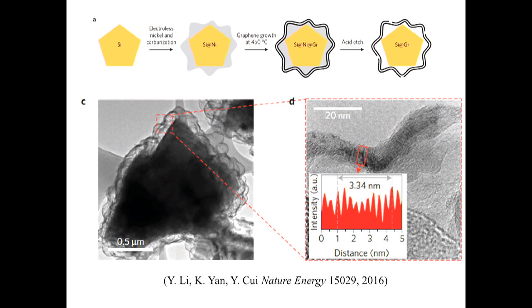Silicon micron particle, we developed synthesis. Doing a nickel coating, get a little bit of carbon coating right there. 450 degrees C, not too high a temperature, turned out this nickel is a catalyst to grow carbon into a graphitic carbon. Actually, nickel leaves the empty space. You see now there's a cage right there surrounding this dark color of silicon. And if you go to high resolution transmission electron microscopy, you can tell it's a graphene packing right there. So let me show you a couple of videos to tell you how amazing this graphene cage can be.